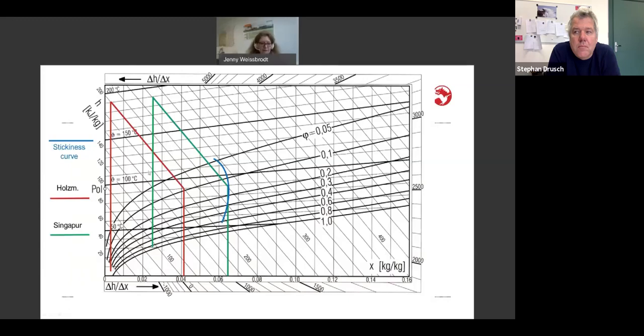I put in this diagram a curve for the drying process in Holzminden in red, in Singapore in green lines, and what I even put in here is a stickiness curve. A stickiness curve can be determined for any component to be dried. You measure the behavior of your powder under different conditions of humidity and temperature, and then find out when your particles start to lump, when you don't have a free-flowing powder anymore, where the lumping and the stickiness of your powder starts.